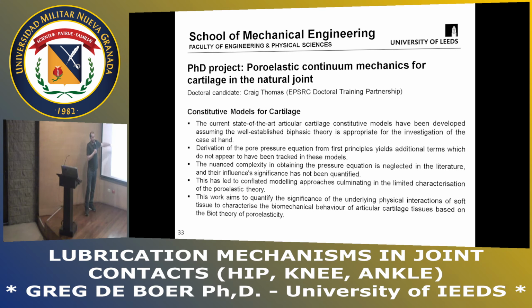But if you look at the state of the art of cartilage models, they're well established in this biphasic theory, which is this coupling of the fluid and solid, which I've been talking about. But the derivation of those equations from first principles is questionable. Okay, they're based on what we call Biot theory, which is, again, a geomechanics type model used for soils and sands and other things like that.